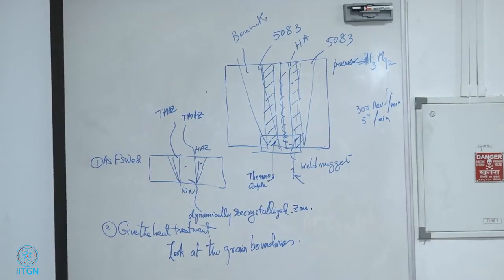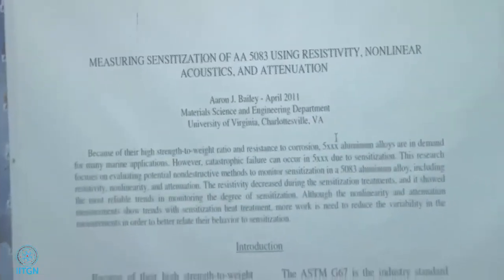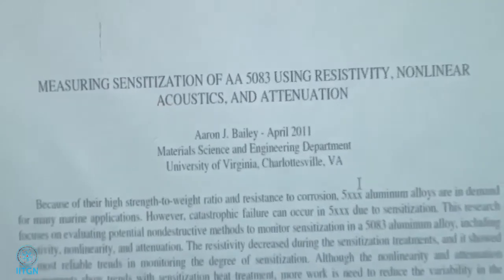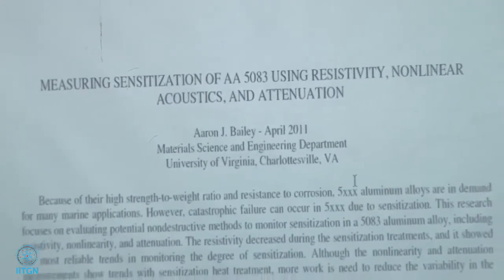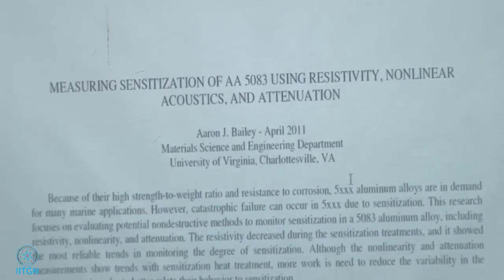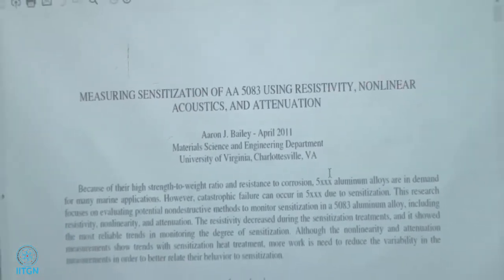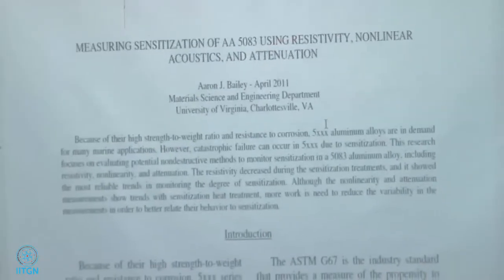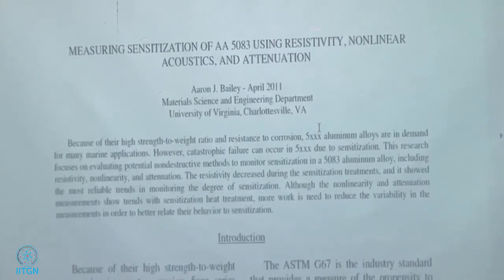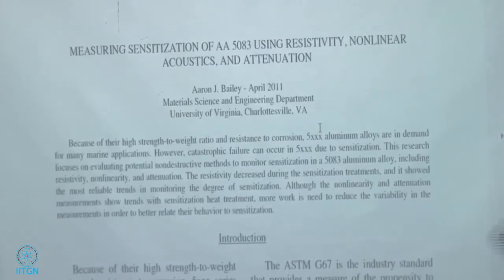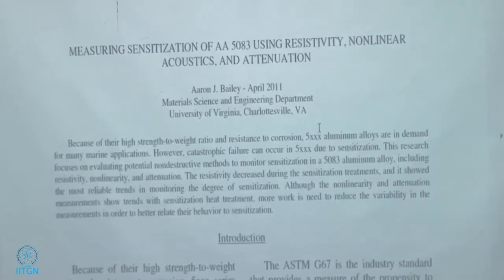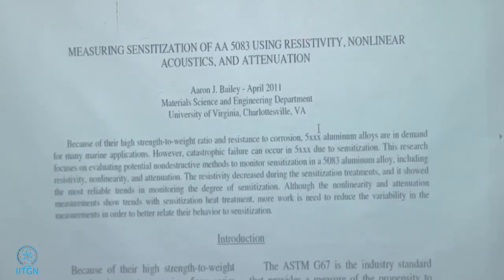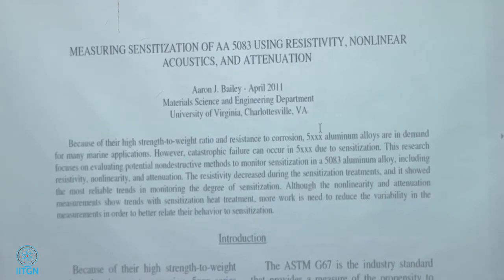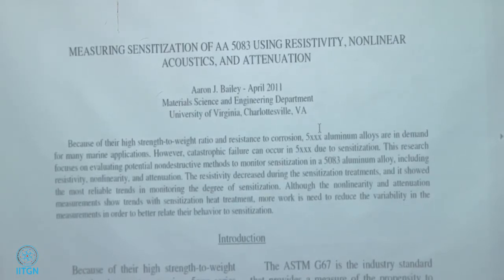There's another paper here also. I just picked it up. Measuring sensitization. As a matter of fact, you don't even have to do all this if you don't want to. Measuring sensitization will be difficult to do. Just use resistivity measurements. Don't worry about nonlinear acoustics and attenuation. I can tell you what it is if you want me to, but not here. It will take up all day. I would do resistivity measurements. That will tell you. Just measure current as a function of voltage, but it has to be very, very sensitive.